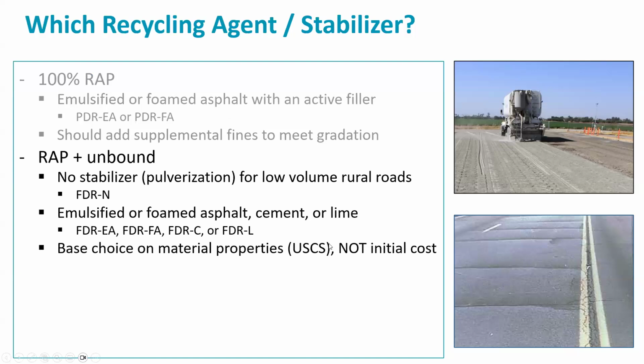If we're going into the unbound layers underneath, we have options. We can do nothing if it's a very low volume traffic and we've got good materials down there. We encourage the use of some kind of a treatment. So if you've got good engineered materials there, then we'll use asphalt treatments on that. If we've got more marginal materials, high fines content, some clays in there, then obviously we'd move more towards the cement.